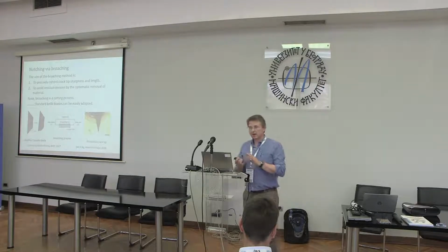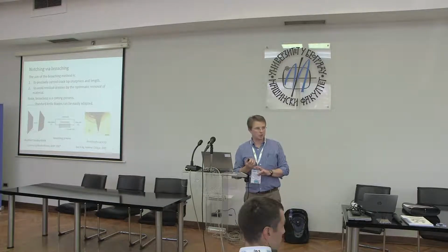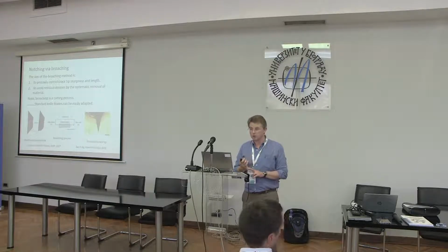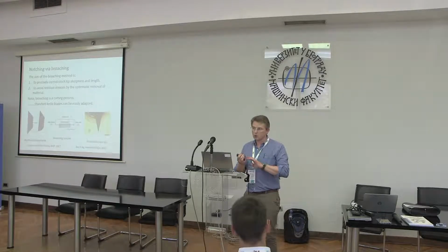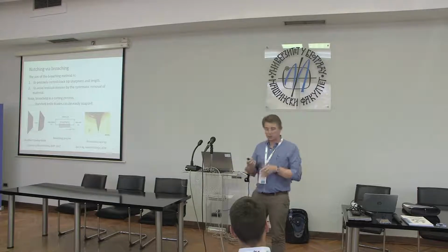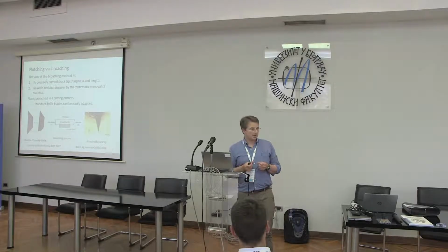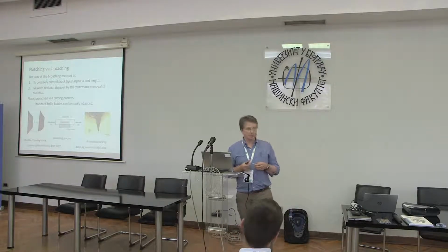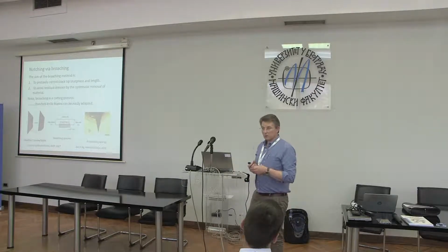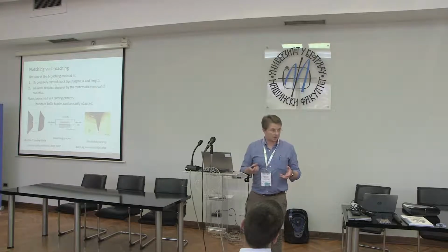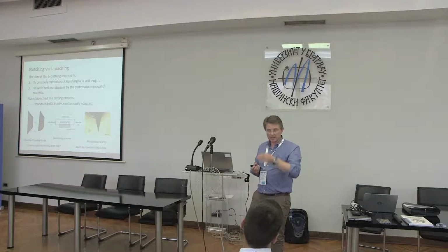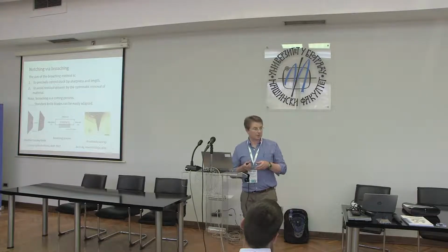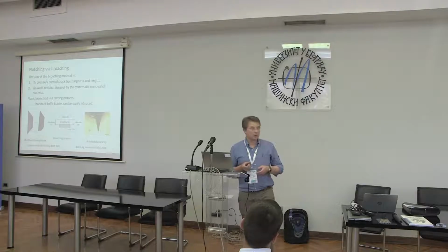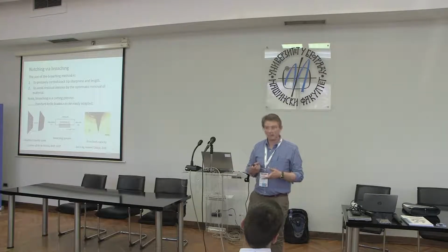So the key idea of the broaching is that you control the sharpness by controlling the tool. You control the direction and length by controlling the motion of the tool during the process, and you completely eliminate residual stresses. Now, the reason you eliminate residual stresses is that this is a material removal process. It's a cutting process. And what you're doing is each time you're taking a pass, you're cutting the material. You're removing that piece of material that may have been modified by the presence of the blade.